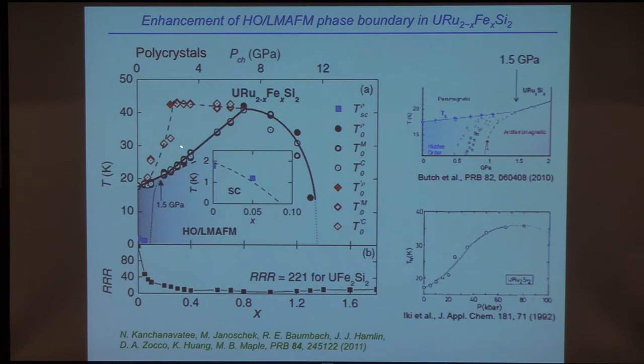There's a kink in this phase boundary that occurs at a chemical pressure very close to the kink that occurs under pressure in the pure compound. So we think this is where the transition from hidden order to large moment antiferromagnetism occurs. And then you see that this goes over a peak very much like the phase diagram does at higher pressures from other work in the past on the pure compound. Okay? So we think then that this is the transition where you go from hidden order to large moment antiferromagnetism.